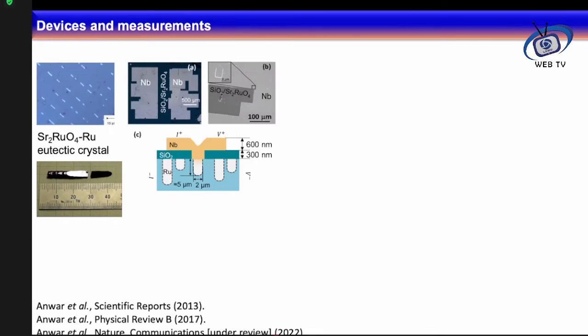And when we grow this material, we get the single crystals in this way, that here we have the strontium-2 ruthenium-4, but there are also some bright parts. Those are the ruthenium metal. So this ruthenium metal is embedded. These are the inclusions. And if you put any other metal at the top of this superconductor, then the electronic connection between the deposited metal at the top of this single crystal is very bad.